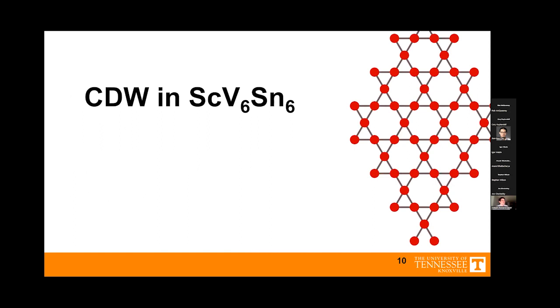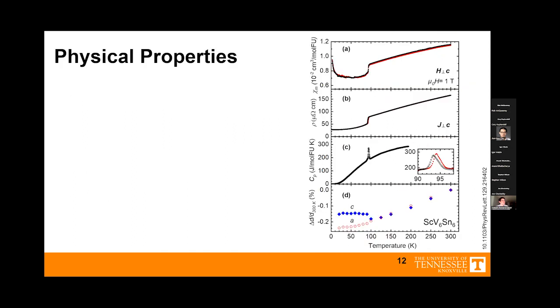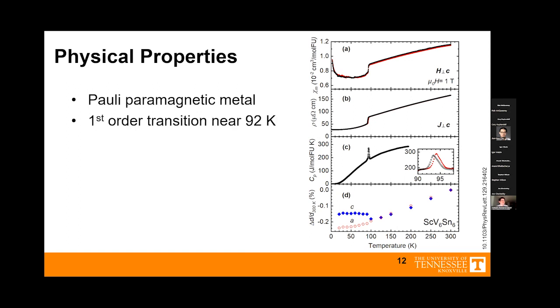So the charge density wave in scandium vanadium tin is different than that in the other vanadium kagome compounds so far. When we made crystals of scandium vanadium tin, Hashitha noticed that there was a drop in the electrical resistance at around 92 Kelvin. Magnetization measurements also showed a drop, although it's just a paramagnetic metal. So we're not looking at an antiferromagnetic transition.